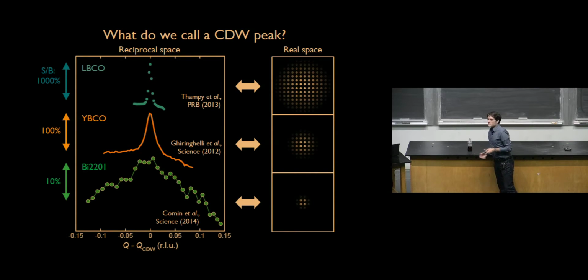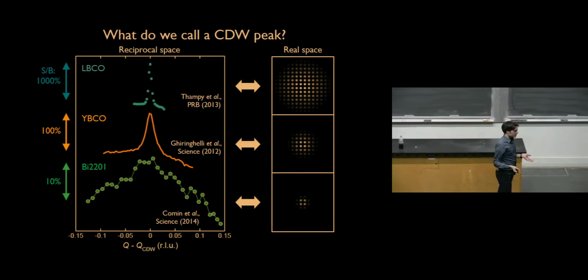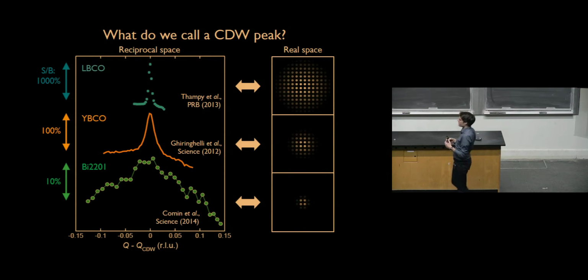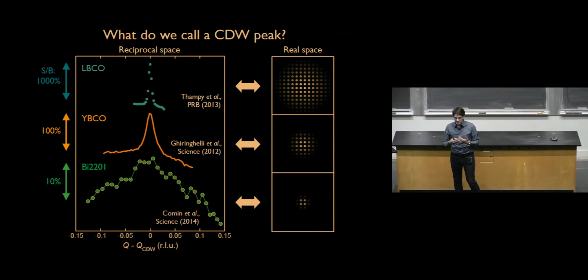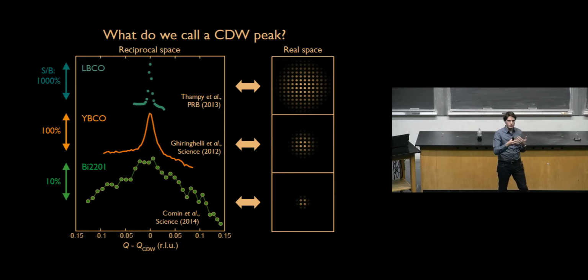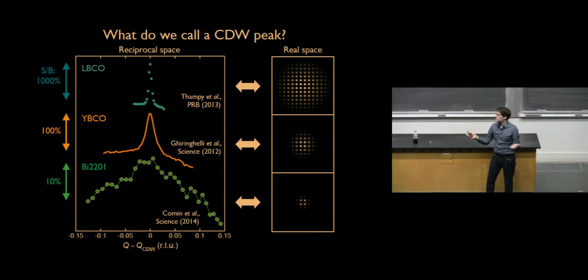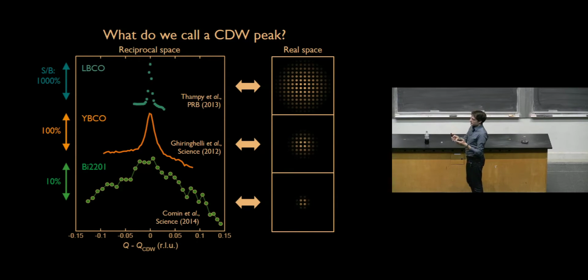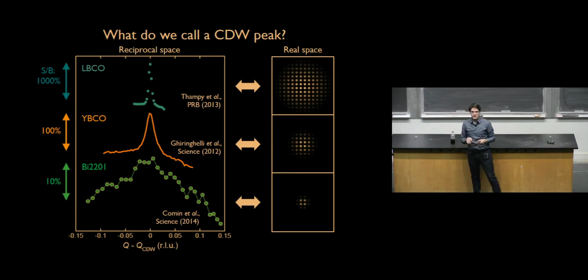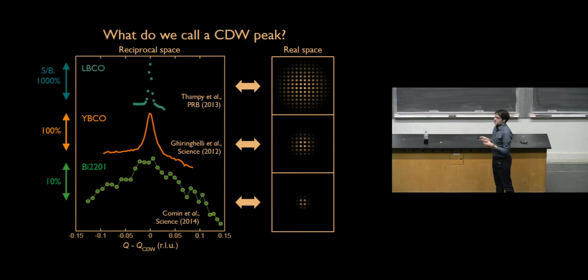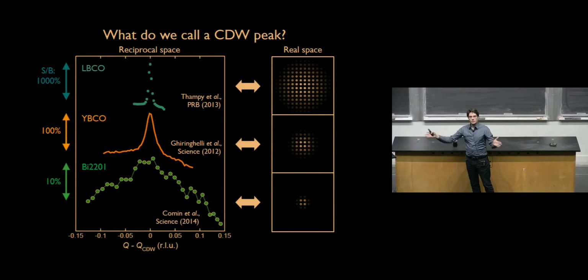One point I would like to make is that when you do crystallography, when you look at things in momentum space, you typically look for things that are ordered. So things that in real space form very well-defined, long-range ordered patterns, like atoms in a crystal. So you expect that the length scale over which the function that you're measuring, say the atomic density or the electronic density, is coherent with itself, the correlation length, is very long. And that is the case for certain types of charge order in the cuprates. And that's certainly the case when you do regular crystallography, because atomic lattices have a very long-range coherence.